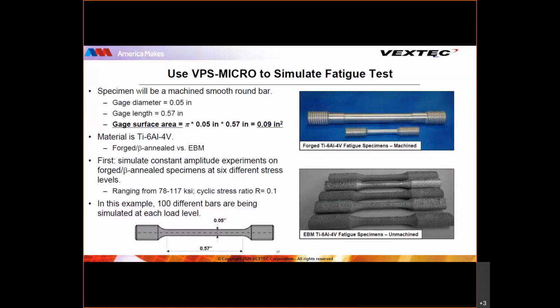And I'm going to use VPS-MICRO to simulate the generation of a standard stress life curve, an SN curve, through fatigue testing. You can see the size and the dimensions of the fatigue specimen in the drawing at the bottom, and the calculated surface area of the specimen's gauge section of 0.09 square inches. And we'll first be simulating the forged specimens, performing constant amplitude fatigue testing at 6 different load levels, so a loading ratio of minimum to max of R equals 0.1.